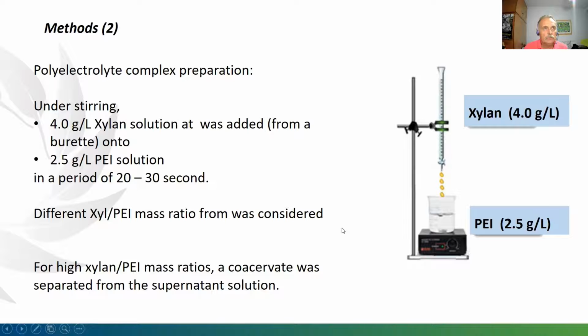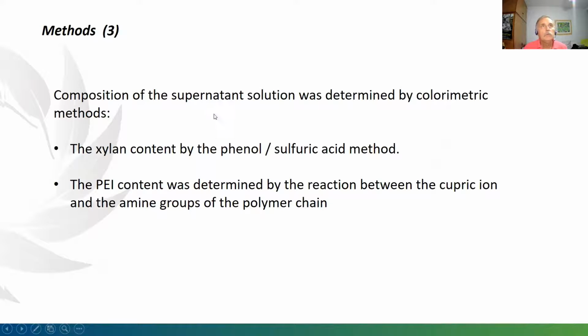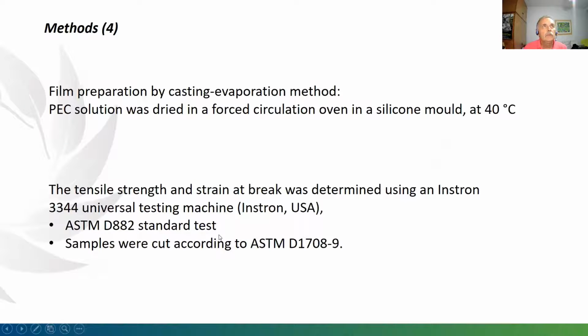And different mass ratios were considered. For high xylan/PEI mass ratio, a coacervate was separated from the supernatant solution. The composition of this supernatant solution was determined by colorimetric method, and film was prepared by casting method, and then it was dried at 40 degrees, and it was analyzed by tensile test using a standard method.